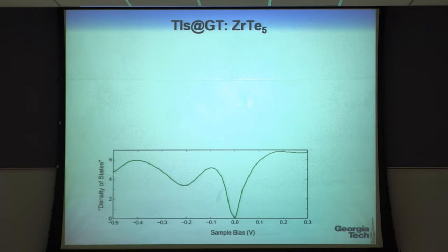Now, how do you start mapping these densities of states again? So this is the density of states. It is dI/dV normalized in a sort of standard way. Here's where the Fermi level is at zero bias. The chemical potential of the tip and the sample are equal.